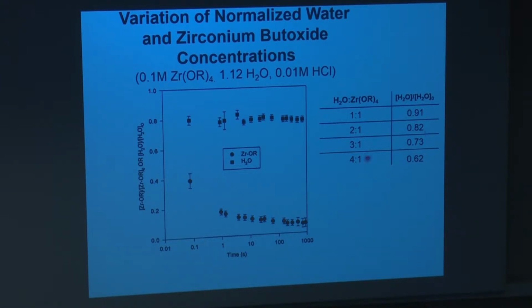One of the issues is typically the first couple of hydroxyl groups can come off very quickly, but the others are a little bit stubborn, and so they don't come off as fast. But what this shows is for zirconium alkoxide, in this case zirconium butoxide, you see a very fast hydrolysis, and you see where probably 90+% of the alkoxy groups are removed. If you look at the water, you see that the water basically stays about the same, which means that initially you get a very fast hydrolysis of the first two alkoxy groups, but then later on you have the alcohol-producing condensation reaction occurring.